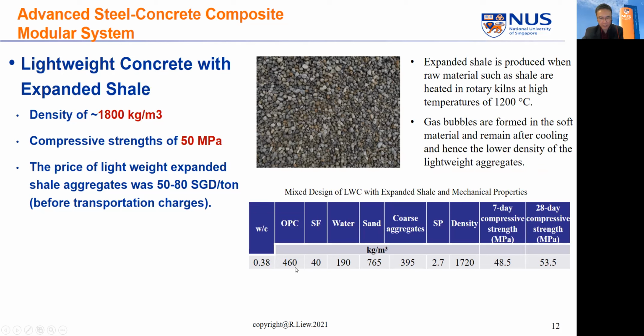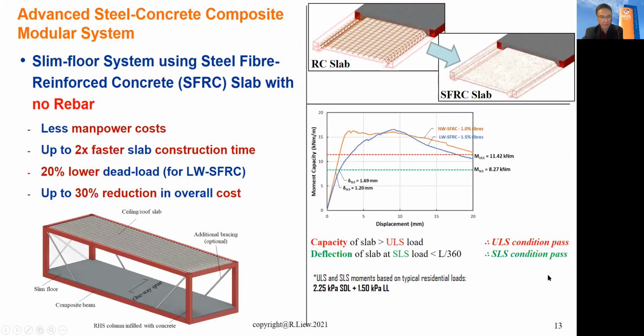And these are actually the price of the lightweight expanded shale aggregate, about $50 to $80 Singapore dollars per ton before transportation charges. And this is a mix design of lightweight concrete with expanded shale, with a water cement ratio of 0.38, the content of OPC, silica fume, water, sand, coarse aggregate, superplasticizer, resulting in concrete density of 1720 kilogram per meter cube, and the 28-day compressive strength of about 53.5 megapascal.